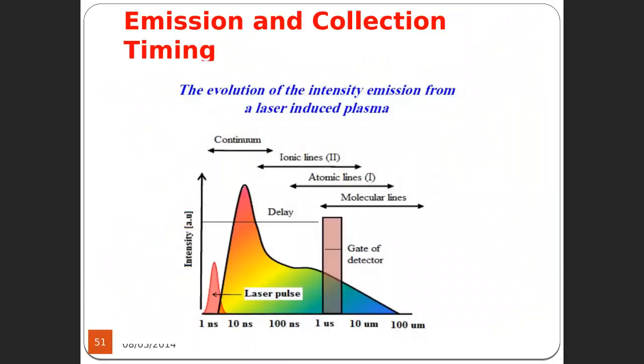But just mention that the plasma is generated after the start of the laser, and in the beginning, within 100 nanoseconds, there is continuum emission. After some time there is ionic lines emission. Maybe after 1 microsecond there is atomic lines emission. After 3 microseconds there is molecular lines emission. Why does this happen? I will say to you, it is a kind of scenario. The scenario is the following.